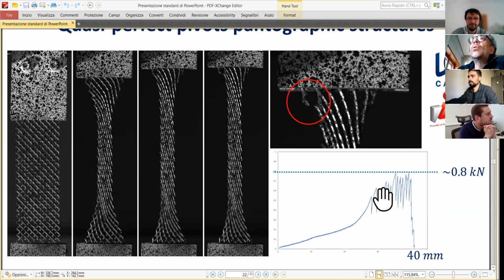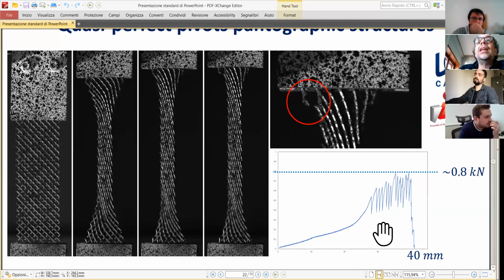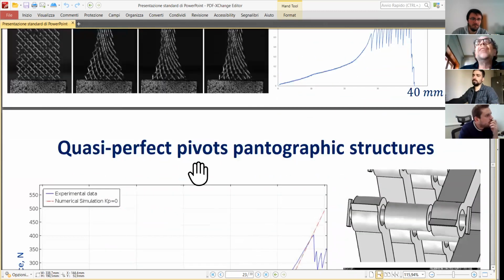So this means if you calculate the area under this plot, you have under this region the energy which is needed for arriving at the total failure of your specimen, and the area under this plot here, say until 25 millimeters, is the energy which can be engaged in the elastic deformation phenomena. So you can consider it the amount of energy which the material can store working without being damaged. So the amount of failure energy is equivalent to the amount of elastic energy. This means that this material which we are going to invent is indeed resilient. It is resisting damage phenomena in a very effective way.